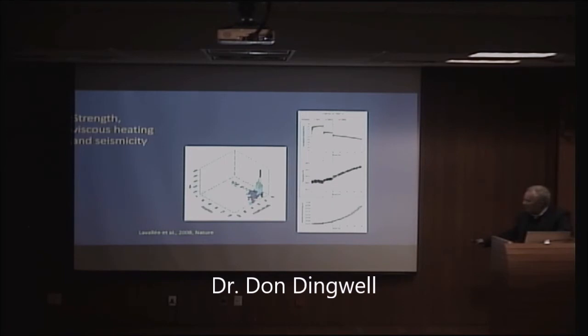And acoustic sensors we can parameterize in terms of the number of events, when they occur, and what energies are associated with them. And what you see here is something that looks, I hope, to you like a catastrophe about to occur, and it is indeed. It's the climb up in acoustic events, which are minor cracking in the sample before it catastrophically fails.